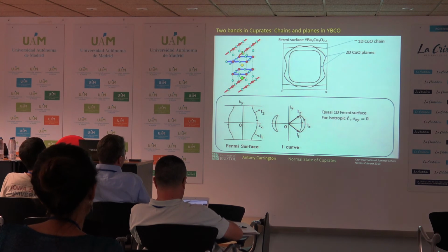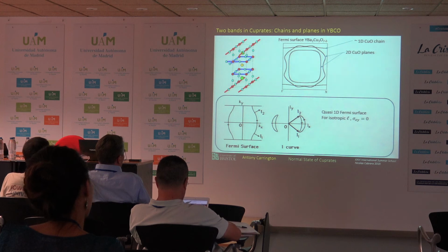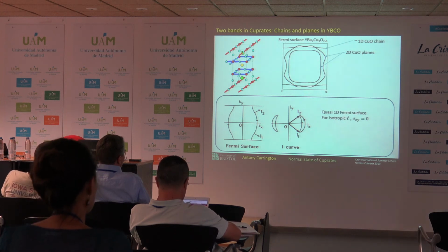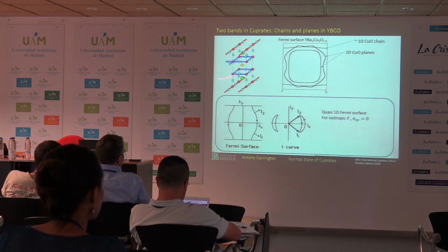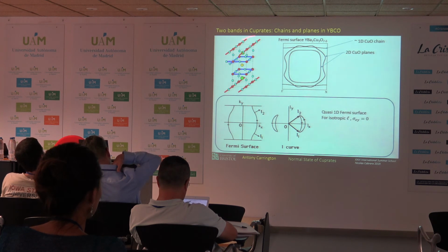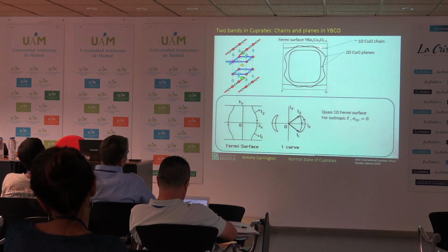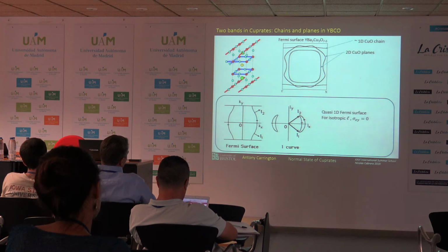Okay, so where two bands actually do come into things in the cuprates is in the compound YBCO. Although this is in many ways one of our favourites, it has this horrible complication that it has our nice copper oxygen planes, but it's got these oxygen deficient planes, which we call chains. They're missing an oxygen here and here, and they give you one-dimensional structures, which on a DFT Fermi surface give you these bands here, and you can see these bands actually cut across the planar band. So we've got two planes. These are the two copper oxygen plane bands, and the chain band cuts across them and hybridizes with them.